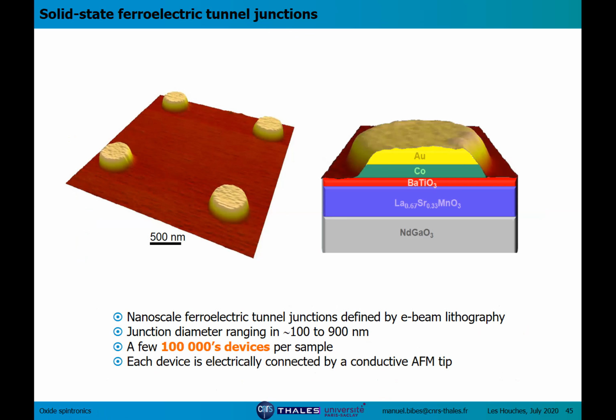So a few years later, we built solid state ferroelectric tunnel junctions, meaning that we deposited top electrodes on top of the barium titanate. Here again, we are using a ferromagnet, but don't pay attention to that for the moment. This is gold and cobalt and gold, or cobalt and platinum, or different metals. These are very small, typically a few hundred nanometers. And we can measure the tunnel electroresistance, the resistance response, by contacting them with a conductive tip.